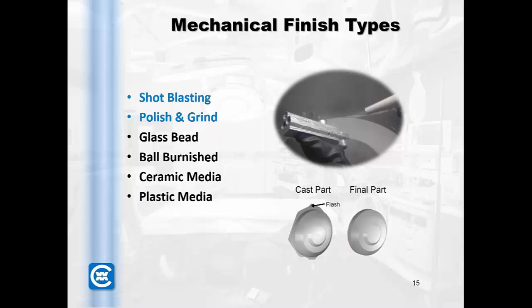And then there's dozens of different types of bead blasting, whether it be glass or steel shot or many different types. And the little image down here shows that when you go through these mechanical finishes, what it also does is help remove some of the small amounts of flash that are contained on a die casting. This shows what could be a before small amount of flash, and then after the mechanical finish, the part is much smoother and the flash is removed. So a couple of different good reasons why mechanical finishes would be utilized.